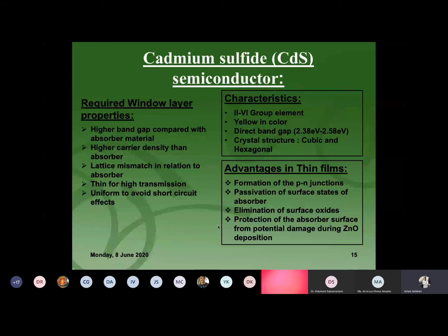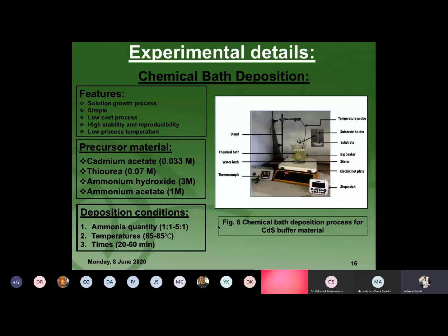So cadmium sulfide is deposited by chemical bath deposition, which is a simple, low-cost solution process. It also has a low process temperature, and the material deposited from this process has high stability and reproducibility.